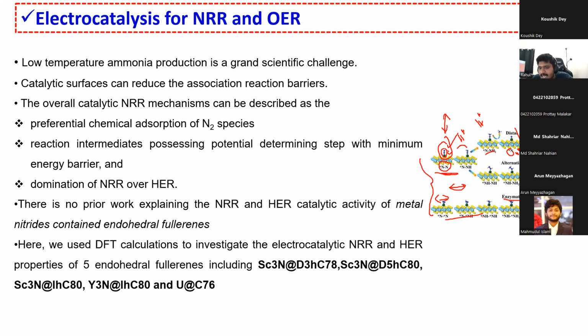Now, to convert nitrogen to ammonia, the first thing is that we have to preferentially adsorb the nitrogen. The second thing is that the pathway should have a very low potential determining step. If it has a very low potential determining step, it can easily convert from nitrogen to ammonia. The third thing is the competitive mechanism between the nitrogen reduction reaction and the hydrogen evolution reaction. Why? Because here it is nitrogen, but we are adding a proton, which is H plus. When we add a proton, instead of sticking to the nitrogen, it can stick to the substrate itself. So there is a competition: whether the proton has the highest binding energy with the substrate or the nitrogen does. That also plays a role in the nitrogen reduction reaction.